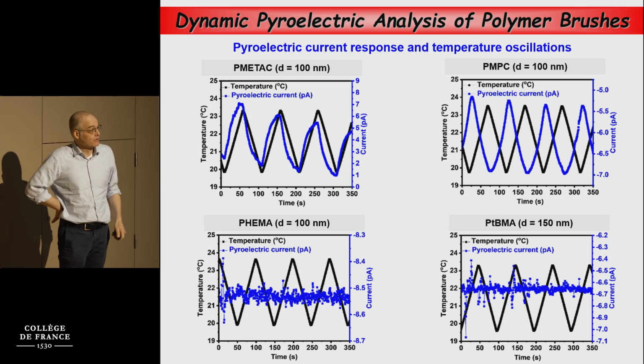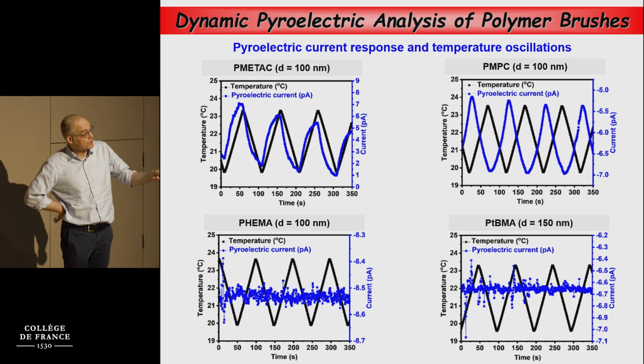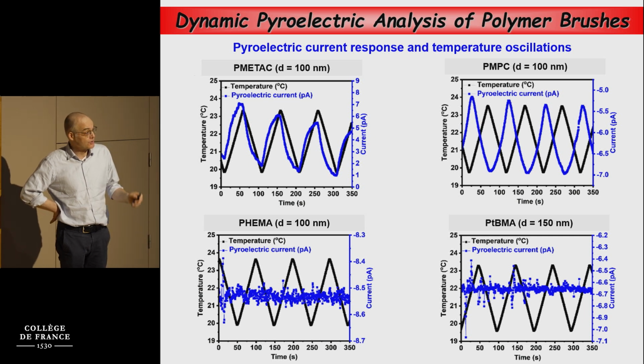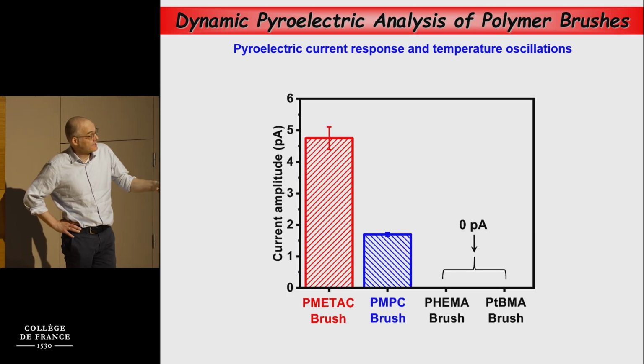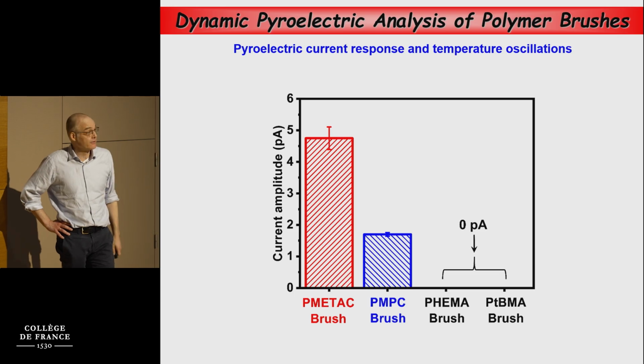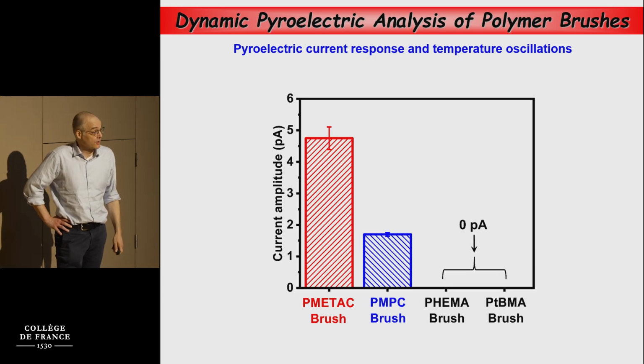So this was an interesting observation. First of all, some brushes show this behavior, other brushes don't. If you quantify this, the current for the strong electrolyte is about 4.5 picoampere, the zwitterion about 1.5, and the other two do not show any significant pyroelectric current.